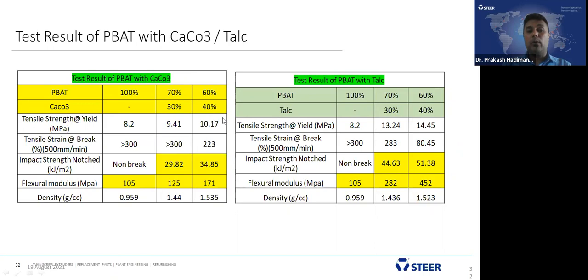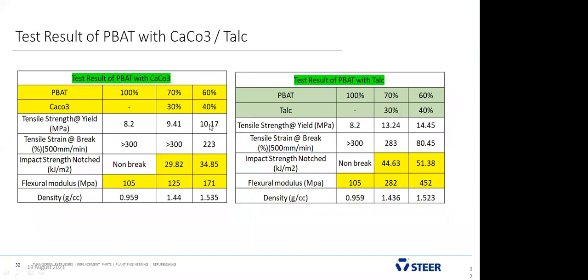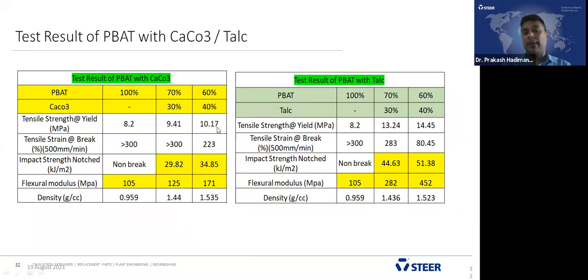If you compare both, we observe there is an increase on addition of calcium carbonate with a virgin PBAT polymer. The tensile is 8.2. Addition of calcium carbonate definitely increases it up to 10.17 megapascal. But when it comes to the talc, there is a further increase compared to even the PBAT with the calcium carbonate. And even impact strength increases.